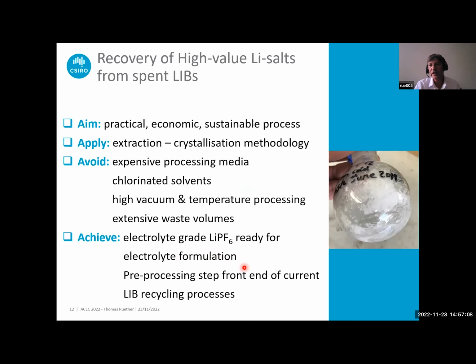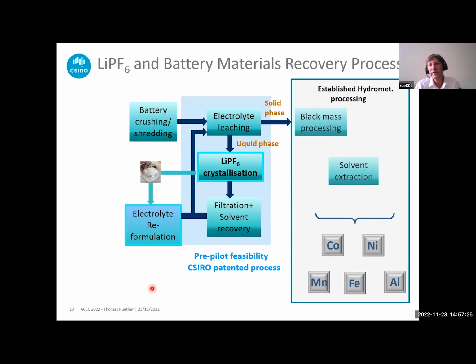So what we want to achieve is a high-grade lithium hexafluorophosphate salt, which can be reformulated. And an advantage of our process is that we can do this at the front end of existing processes. Here's a block flow diagram, typical shredder unit at the front end, which is used in other processes. And then the shreds will be leached to extract the electrolyte. The solid phase can then be simply filtered off and be put into existing hydrometallurgical processes.